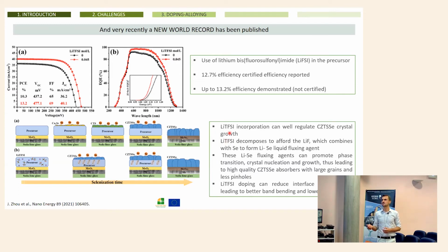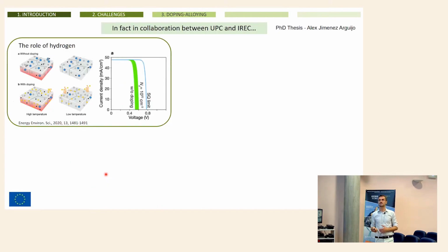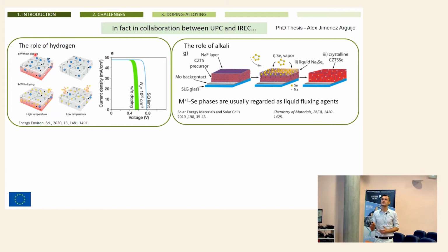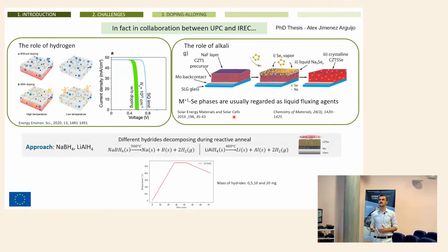I don't think that this is the only reason for lithium. We have evidences that lithium is also playing a more important role in kesterite, or an additional role to those. This is true, okay, but there is an additional effect of lithium. So to demonstrate it, we think that lithium has a similar effect to hydrogen. So we decided to design experiments using this kind of compounds: sodium borohydride and lithium aluminium hydride.